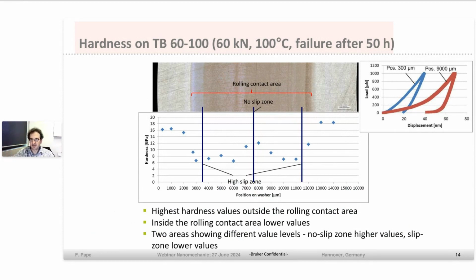And for the elastoplastic material behavior, on the right, there are some exemplary nano indents outside of the contact zone. We see that there the material behavior is less plastic, and in the middle of our bearing washer, slightly in the high slip zone, you can see a very deep indentation and also a large amount of plastic behavior for this tribofilm. To gain more information, we did some nano scratch tests.